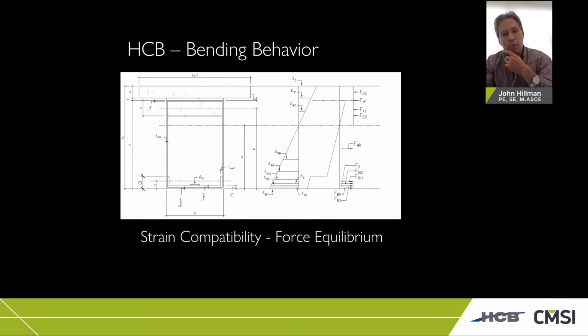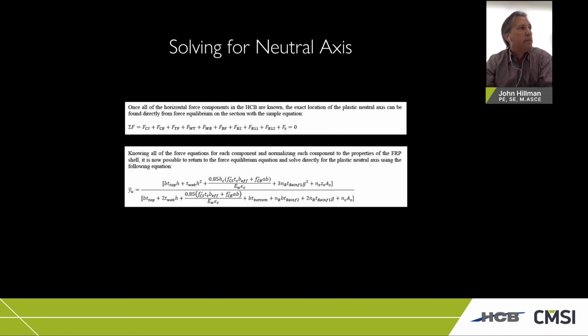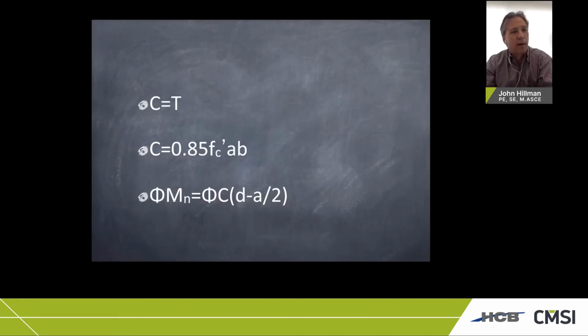But now we've got a lot more components because we've got the FRP components, we've got the strand in the bottom, we've got a top flange, a bottom flange, the concrete flange. But still, we can look at the linear strain distribution and calculate the forces in each one of these components. You can set the horizontal forces equal to 0, sum for the moments, and you get this nice simple equation that gives you the ultimate neutral axis of the beam. And that's something that'll keep you busy on a Friday night when you've got nothing better to do. But I'm kind of lazy, so I look at it this way.